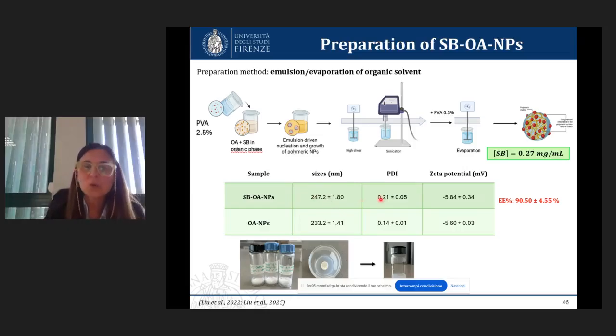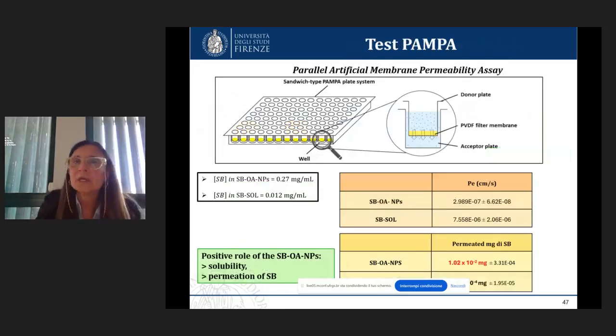The physical chemical parameters of this nanoparticle are very good, because we have a size around 200 nanometer, a good homogeneity of the samples, a good zeta potential, and a high encapsulation efficiency of silibinin inside the nanoparticles. For this system, we tested also the possibility to obtain a dry product by freeze drying process, and we obtain a solid formulation, and after the addition of water we obtain again the colloidal dispersion of the silibinin nanoparticles.